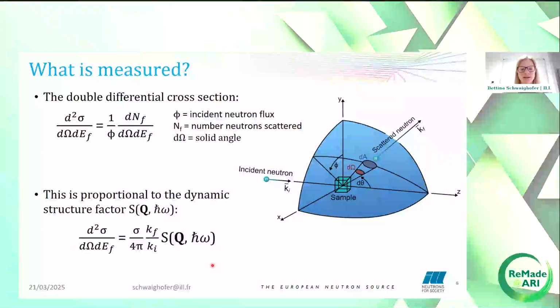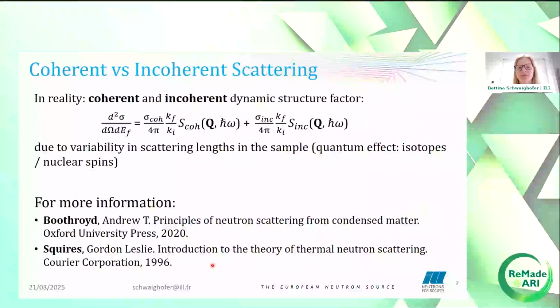This equation here is only valid if we have a single isotope with a zero nuclear spin in the system. This is, well, generally not the case, which means that the reality of neutron scattering is more complicated. A second contribution to the dynamic structure factor appears, which is called the incoherent dynamic structure factor.